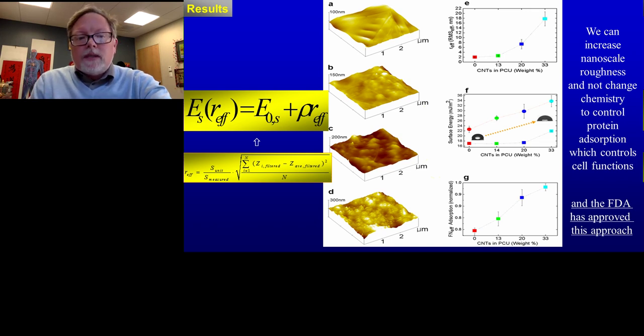We know what E sub 0, comma S is. That's the starting surface energy of polyurethane. We can calculate that using contact angles or many other scientific methods. What we then solve for is that R_eff. What that means is effective surface roughness. So that effective surface roughness is expanded in the equation below, and it's written for the Z height.